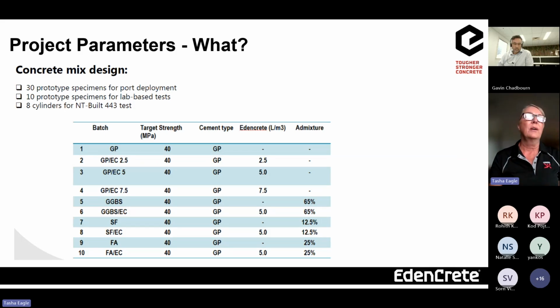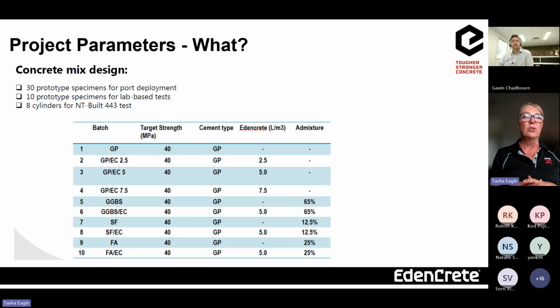So what are some of those results that I mentioned before? So some of the parameters in this particular project that we've seen, there's a bit of information up here, but essentially, and Kod may touch on this a little bit more, there's been 30 prototype concrete specimens that have actually been put out in the port in the water, similar to that image you saw earlier. Those images were 40 years old and have been there for quite some time, but these ones have just been deployed this year. And the beauty is we're actually going to get to see and monitor these results, which is what Curtin University will be doing alongside Rohith in terms of the durability aspects we're achieving with the control mixes versus the carbon nanotube technology in these 30 specimens over a 1 to 5 year period, which is really, really valuable information for our industry.